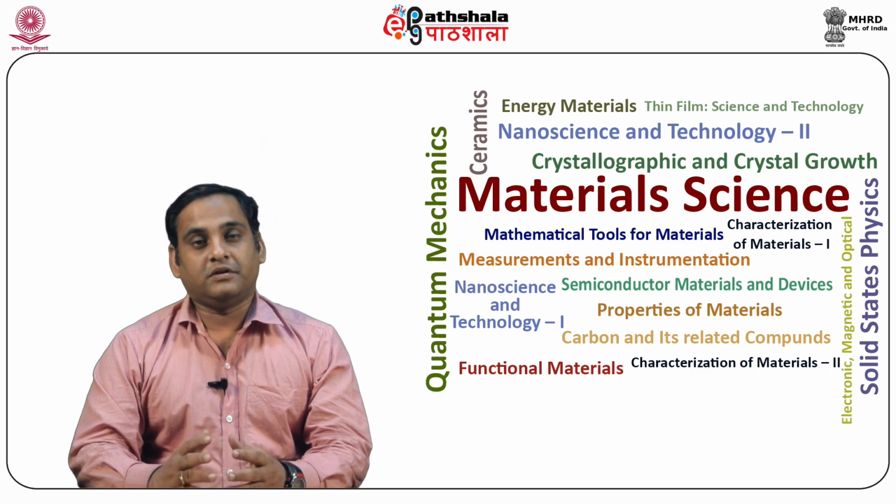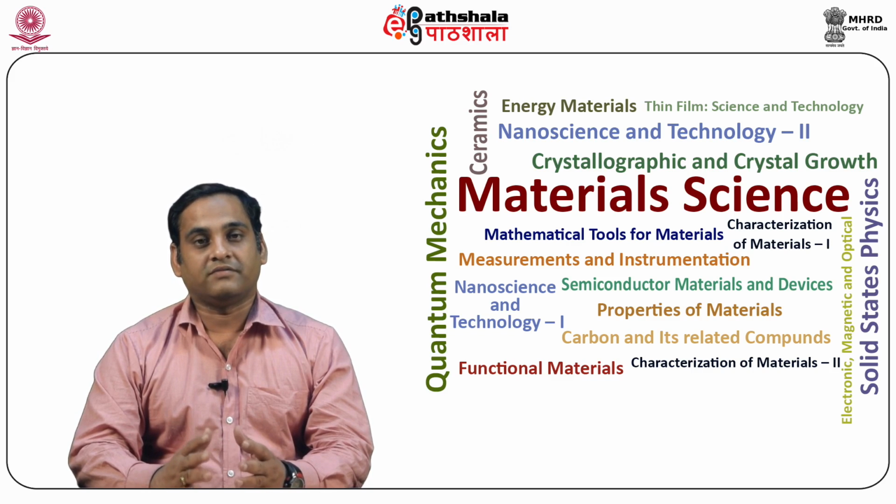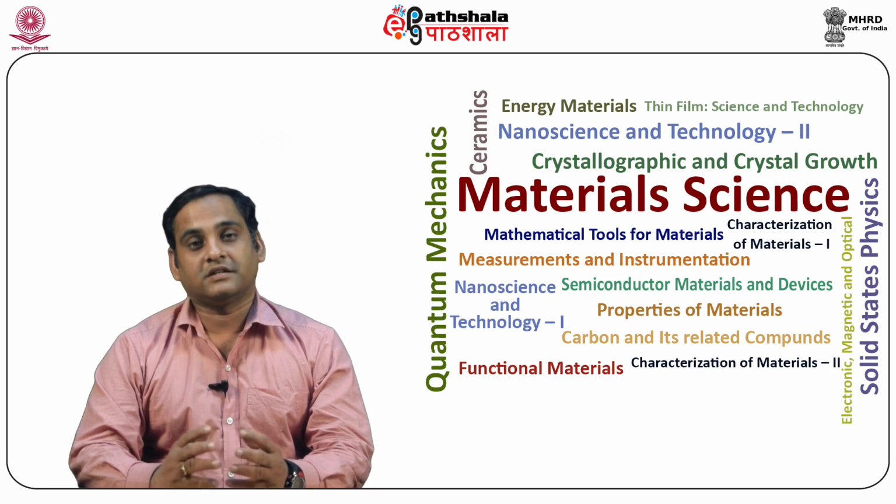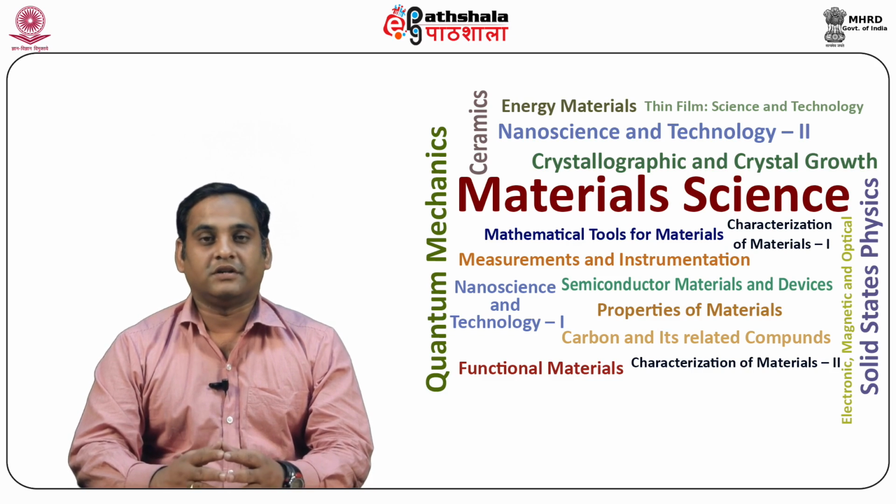Alternatively, there may be vacancies in the structure produced by deviations from stoichiometry, so that there are present excess positive ions accompanied by negative vacancies, or excess negative ions accompanied by positive vacancies. Thus, when excess zinc is present in ZnO, it takes on a yellow color, whereas excess lithium in LiF turns the crystal pink, and excess potassium in KCl makes the crystal appear violet.